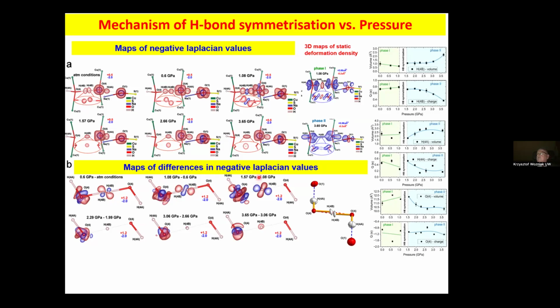And when we go from 1.08 to 1.57, suddenly we have like a completely reverse polarization. We now are observing localization of electron density where we used to have depletion, and we see depletion of electron density where we used to have polarization. And when we go to bigger pressures, this electron density starts localizing at the center of this hydrogen bonding. So with this kind of maps, we see more. And this is perfectly in line when we observe how volumes and charges of this hydrogen atom or oxygen atoms are changing. So the picture is very consistent.